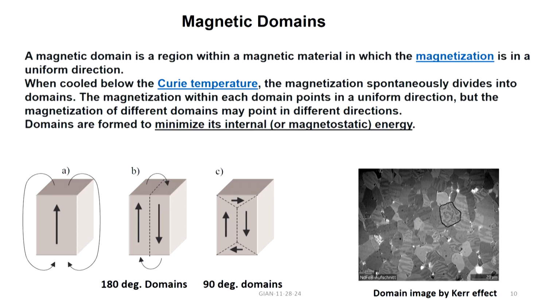Okay. So, all the way left, this is a ferromagnet where the moment is all in one direction. If you look at the field lines, they will travel through the air surrounding the material, and that is not the state of minimum energy. Instead, the middle one shows this splitting into two different orientations, up and down.